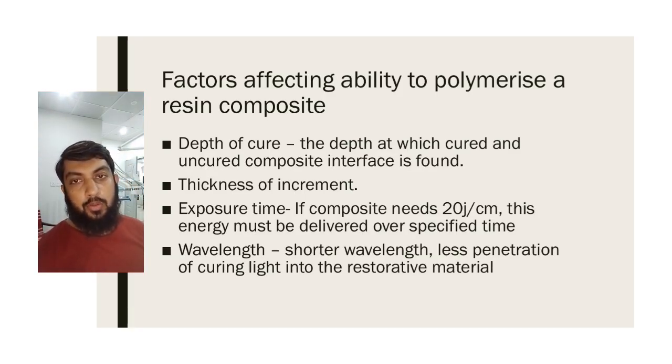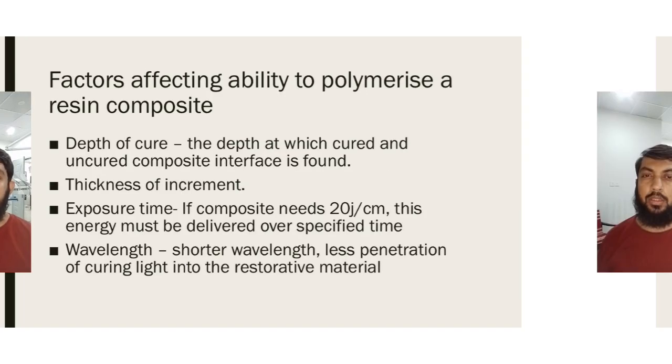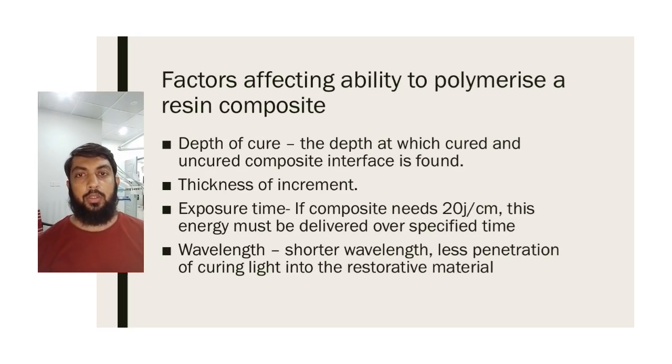If your increment is not 2 mm or less, if it is thicker, like 3 mm, it is not going to be fully cured. If your curing light is not fully charged and it just turns off before the roughly 30 seconds time, it is also not going to cause full curing or depth of cure. It will leave small chains of polymerization. If you are not using the appropriate wavelength, it will also not penetrate the increment of composite fully, so the cure will also be compromised.